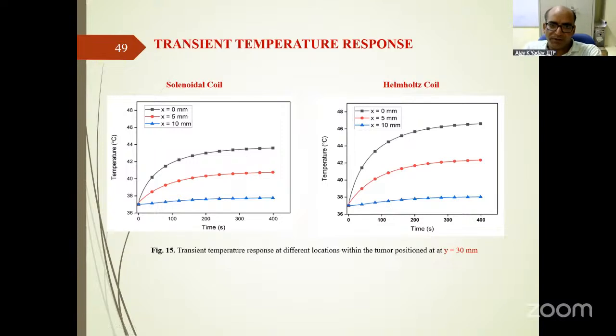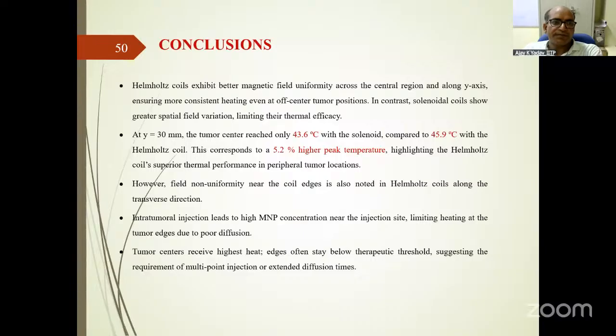So the Helmholtz coil is showing better performance compared to the solenoidal coil. So this is the final conclusion. Helmholtz coils exhibit better magnetic field uniformity across the central region and along the y-axis, ensuring more consistent heating, even at off-center tumor positions. And at y equal to 30 mm, 43.6 degrees Celsius we are getting in the solenoid, whereas 45.9 degrees Celsius we are getting in the case of Helmholtz coils. So this much rise is there additionally, with the same magnetic field. We are not changing those parameters on that side.